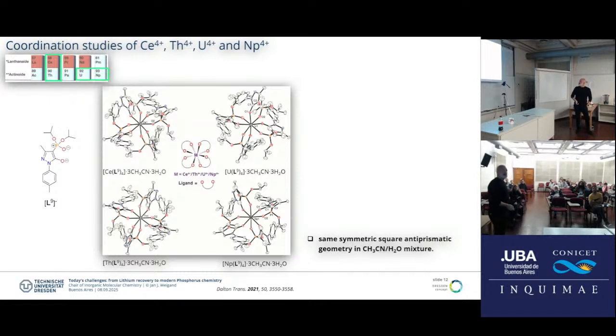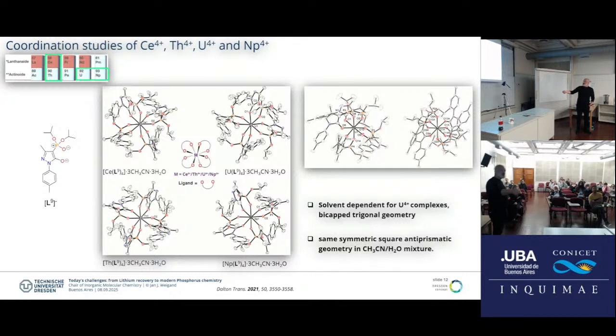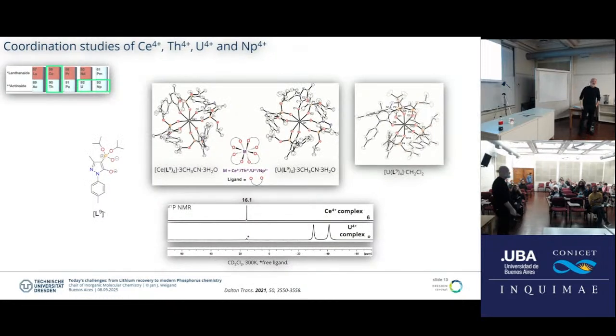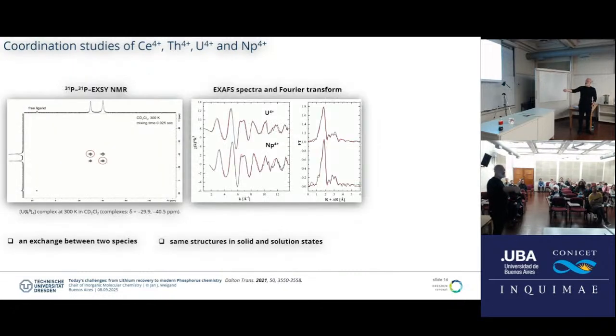Why I'm showing you this, because again you get very nice coordination complexes. You have 4 ligands around one of the centers, and we can of course also follow the formation again in NMR. Paramagnetic still is not a problem there, and so we also did a lot of interesting exchange experiments to understand the speciation in solution, and also we did the XAS spectra with the collaboration of our partners.